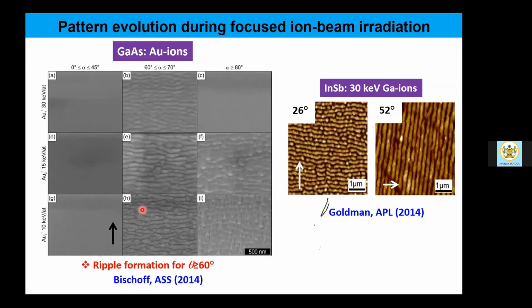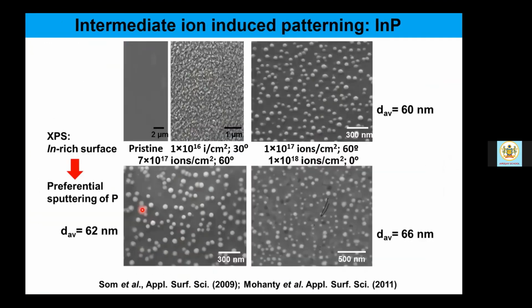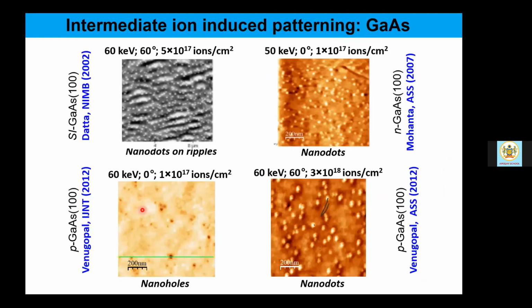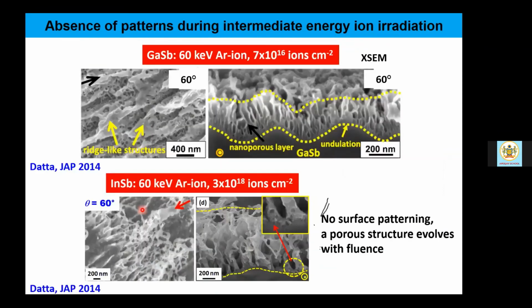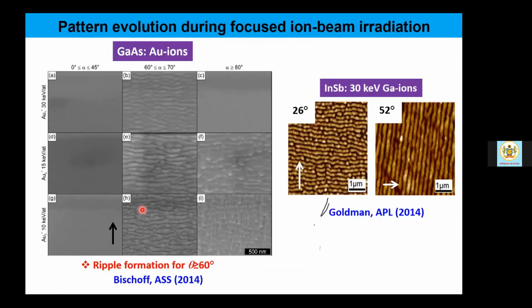Again, we saw that in case of gallium arsenide, very different kind of patterns evolved at tens of keV ion energy. But when we take help of this focused ion beam as a tool to create patterns, we get to see this kind of pattern formation using gold ions, of course, instead of argon. So up to 45 degrees, the surface remained flat. Starting from 60 degree to 70 degree, ripple patterns were evolved. Okay.